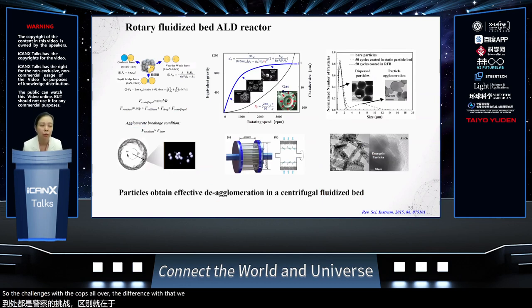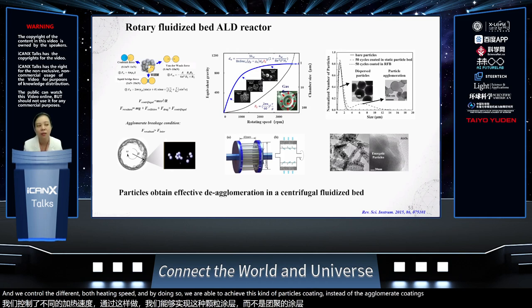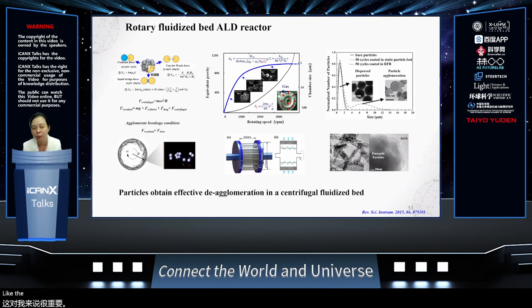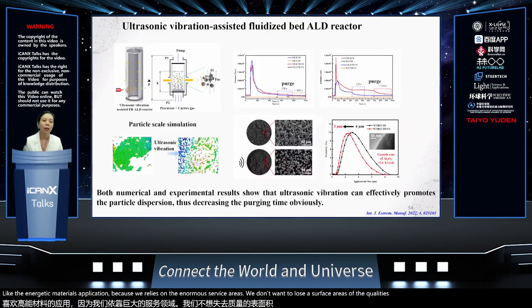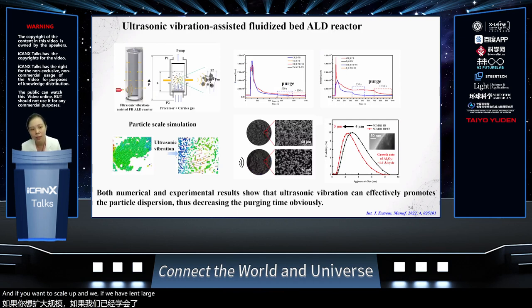So with that, we ran a couple of reactor studies for our own research. For particles that are really tiny, we have to find forces to break the soft agglomerates. Here we utilize rotary fluidized bed reactors, and we control the different rotating speeds. By doing so, we are able to achieve particle coating instead of agglomerate coatings. This is very important for a lot of energetic materials applications, because we rely on the enormous surface areas. We don't want to lose the surface areas for the coatings. And if we want to scale up to larger sizes, here we utilize the ultrasound vibration-assisted fluidized bed ALD reactors that we designed in house.